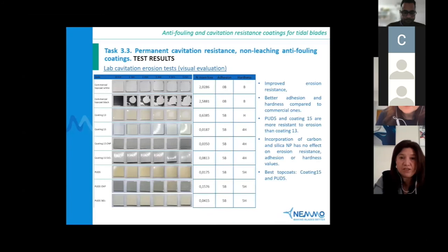For the cavitation erosion test, as I said, we performed the studies in our laboratory, and from the different samples that we tested, including carbon nanoparticles and silica nanoparticles, we can say that there is an improved erosion resistance in the coatings that we have prepared. There is a better adhesion and hardness compared to the commercial ones, the two at the top of the image. And we also see that coating 15 is more resistant to erosion than coating 13, although both of them are solvent-based 2K